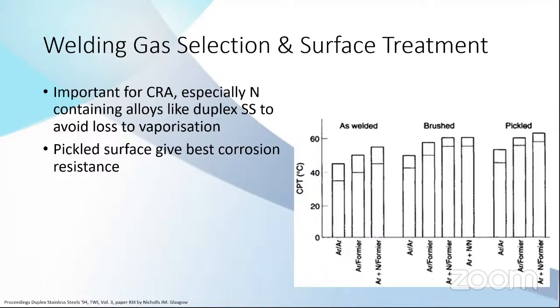Also, if possible, it's recommended to always pickle the surface because it removes all the contaminants and renews the oxide layer on the corrosion resistant material. This is an example of welding gas selection and surface treatment for duplex material. As you can see, this is the CPT, same as before, the critical pitting temperature. Higher is better. This is as welded with argon, and with formier, argon-nitrogen, and formier. When you weld with nitrogen, it has better corrosion resistance.